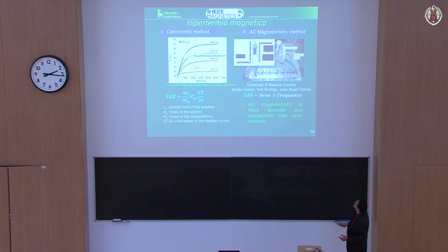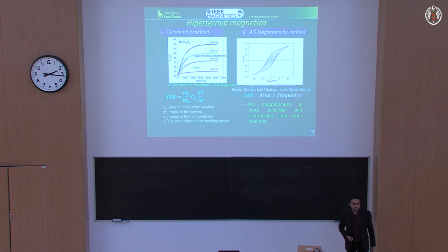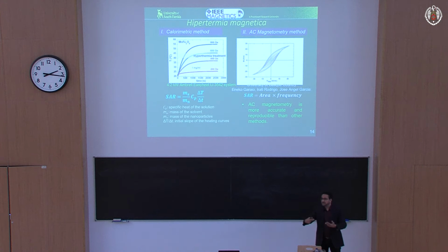So their data looks like this. They are measuring the hysteresis loops. You don't need to achieve saturation. You can get it from the minor loops, okay? And what we do is that we make a comparison of the SAR, and this is why we have our Basque postdoctoral fellow with us who was doing all this exchange, Javi Alonso. So basically, we compare the SARs and we make sure that there is a reliable match between the SAR values you get before we take it to the biomedical stage, biological stage.